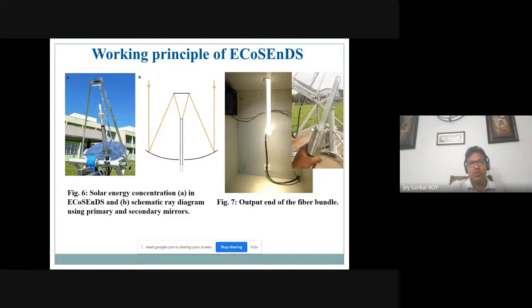The working principle that I told you: solar light falls on the primary mirror. It is a parabolic, then reflected back to the secondary mirror here, and then reflected back to the top of the fiber bundle, and the fiber bundle collects the huge energy. You see on the right there is a picture of the other end of the fiber bundle, where you see very high light, but you cannot judge from this picture, because we took it in daylight. This is the fiber outlet, from where you can get the highly concentrated sunlight.